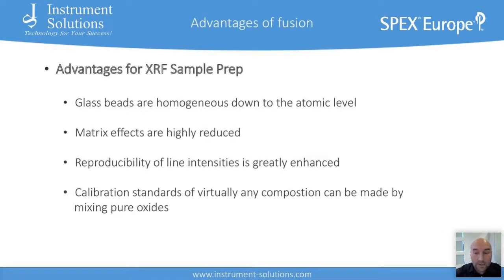Advantages of the fusion for XRF sample prep. Of course, XRF is a technique that implicates a lot of matrix effects. The glass beads are homogeneous down to the atomic level, so you have a very homogeneous sample to analyze. Matrix effects are highly reduced, partly because of the dilution of the sample. The reproducibility of the line intensities is greatly enhanced, and calibration standards can easily be made of virtually any composition by mixing pure oxides with flux and then fusing this into beads. Then you can make very good standards.